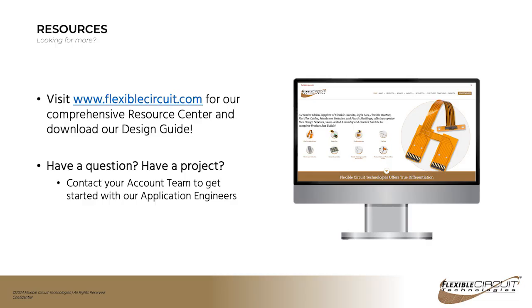And so what we typically do is calculate a bend ratio, which is the ratio of the bend radius to the circuit thickness. And what we recommend in IPC 2223 is for single and double-sided circuits, 10-to-1, and for multi-layer circuits, 20-to-1. And those are just guidelines, and they're not hard set rules.